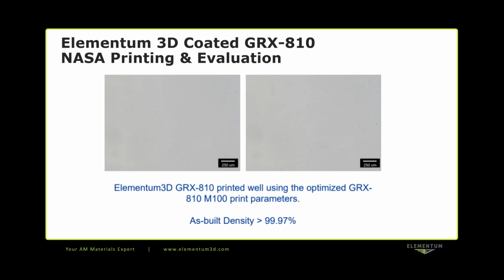Looking at our printed material, NASA did an evaluation where they took powder that we produced, gave it to Dr. Smith at NASA, and they did testing, printed this on their EOS M100 system using their parameter set, looked at the microstructure, looked at the as-built density, found greater than 99.97% as-built density, which is very good for any laser powder bed material.